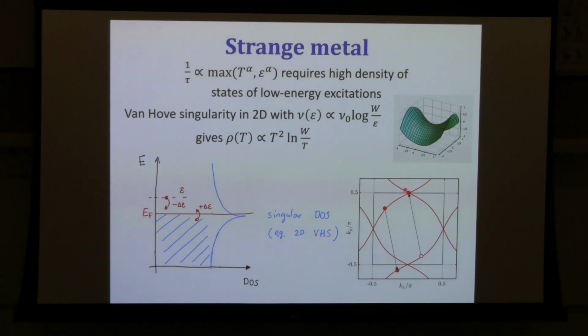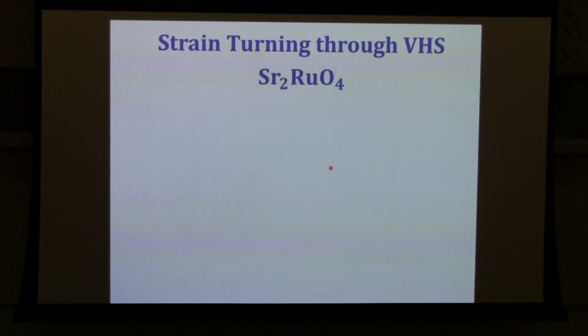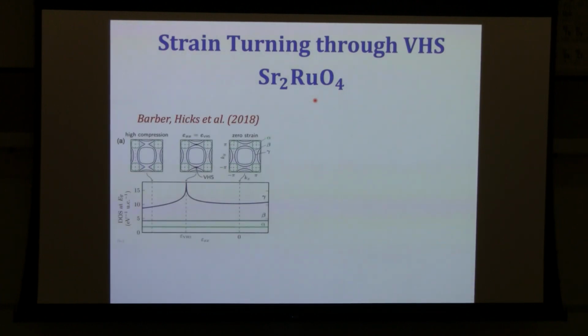So thinking about this was actually triggered by an experiment. It turns out that in certain systems, you can really do this. You can really tune your Fermi sea to be at the Van Hove point. So this is actually how it's done. It was first done in this material, strontium ruthenate, which is a very interesting material for various reasons.